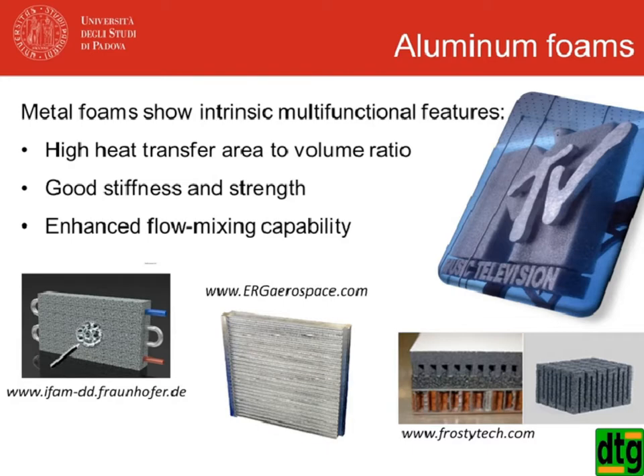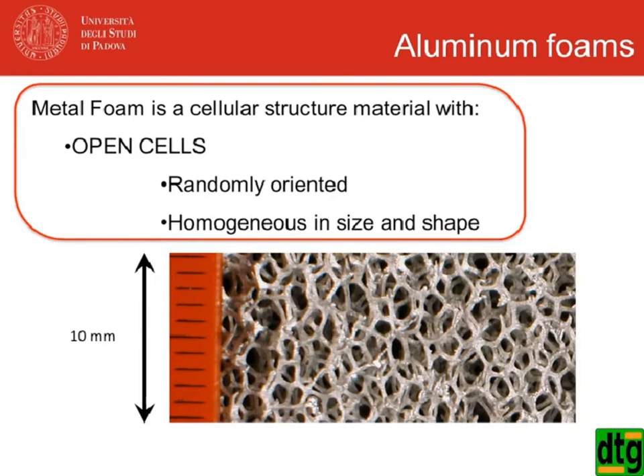Here you have some images taken from the web on different applications of metal foam, and of course something also very fancy like the MTV Music Television logo. Metal foam is a cellular structured material with open cells, so the fluid can move through the porous structure, and these cells are randomly oriented and homogeneous in size and shape. The foams are usually identified by two characteristics: the number of pores per linear inch, PPI, and the porosity, so the ratio between the void volume and the total volume.